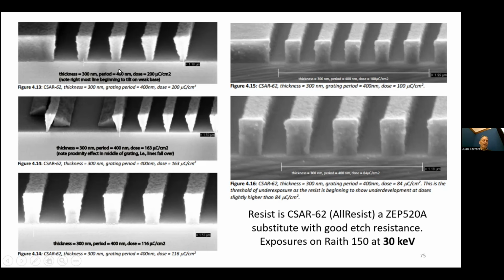I point this out because Juan did these beautiful cross sections and you can see what's happening. If we looked at an aerial view of the same thing, we might not see a huge amount of difference. We'd see the line width changing and the gap changing, but we wouldn't realize that lines were starting to fall over because of this. So if you get the dose dead on, then you get something like this, and you get this beautiful, nice rectilinear cross section of the lines. And this is all done at 30 kV.